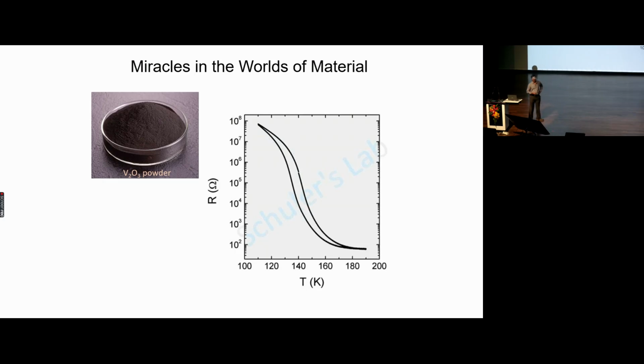For example, you can think immediately, if you see this, that it can be a very good temperature sensor, because if I only monitor this material over this region, the conductivity changes so rapidly with temperature that I can have a very accurate measure of what the temperature is. That would surely be one of the applications. There will be many other kinds of applications, and in fact, a cousin of it, not V2O3, but VO2, and a few others, also play an important role in photochromic glasses, using properties very similar to this. So these are another subclass of materials that have been puzzling us, quizzing us, for the last 5 decades, people are trying to understand why they have such spectacular changes in property, going from a highly insulating state to a highly conducting state.